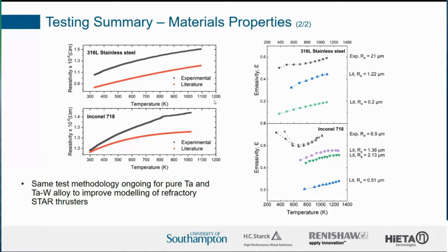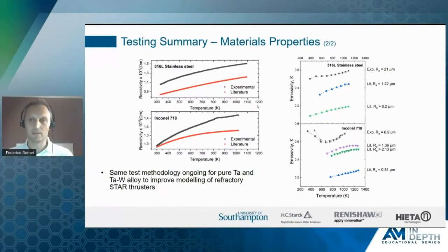So we are actually conducting the same test setup for the refractory metals, both for pure tantalum and tungsten alloy. I want to stress the fact that we didn't do this just to improve the models, but to then be able to use those to optimize the design of the Resistojets and really achieve the maximum possible temperature of the gas.